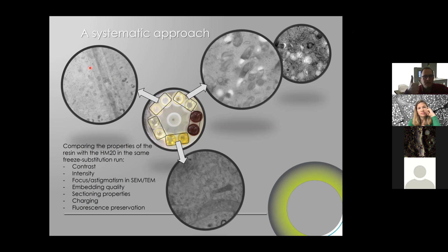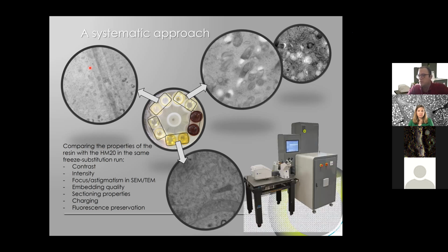I was trying to have the same type of sections, same thickness, trying to fix it to 70 nanometers, and the same parameters on the TEM. None of these sections were post-stained. So basically I was just taking the sections and going to the electron microscope to remove as many steps as possible so that it would be somewhat comparable. And so I did that over a large amount of samples. All the samples were high pressure frozen locally, so that we could always make sure that we had the same parameters.